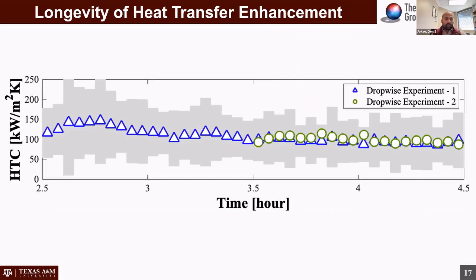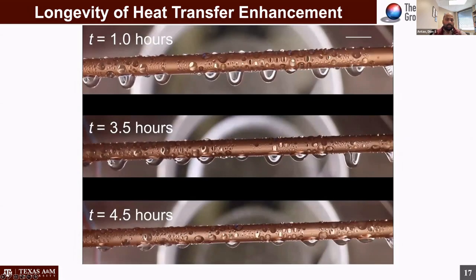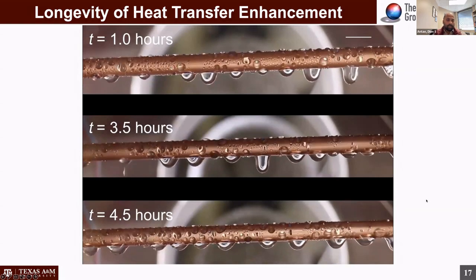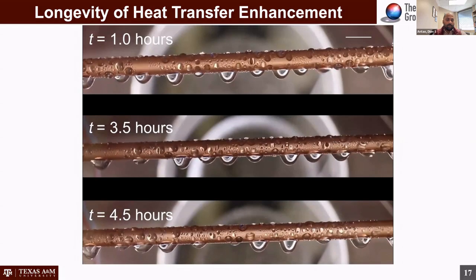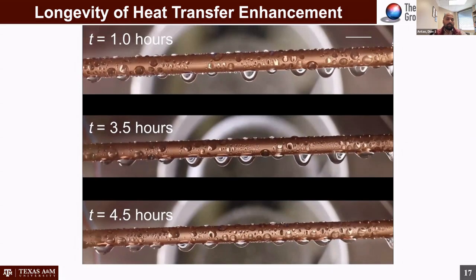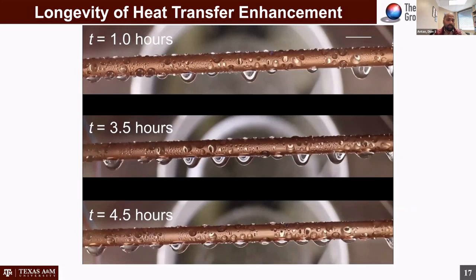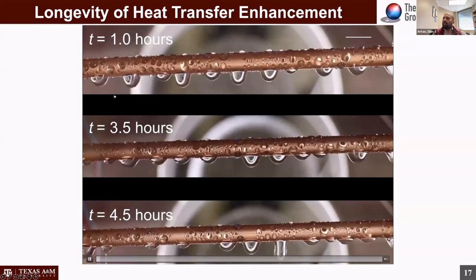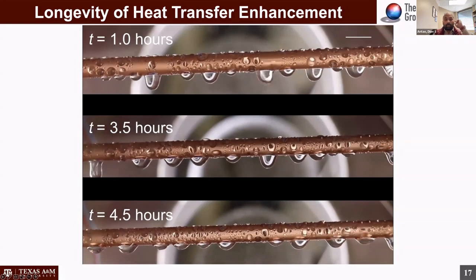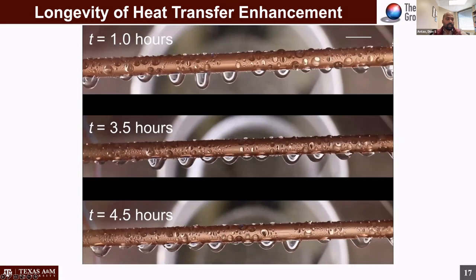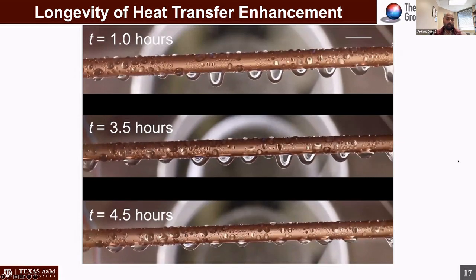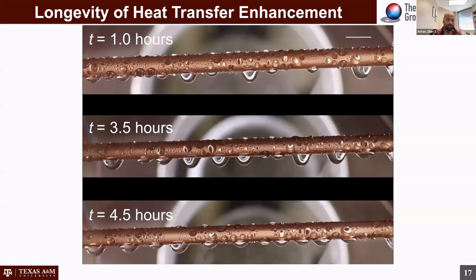We did the experiment, like I said, over about 4.5 hours. All the data was collected right up to about 2.5 hours, and then we just ran the test for another 2 hours to look at the change in heat transfer coefficient over time. And as you can see from the data here, there is almost no change in the heat transfer coefficient within the uncertainty. Again, the uncertainty is pretty high. But if you look qualitatively at the droplet departure sizes, there is not much of a difference between the start and end of the experiment. And so it tells us again, not sure why this video is not looping, but it tells us that the coating has not been damaged too badly during this time, or nothing that can be measured in the timescale that we tested them so far.